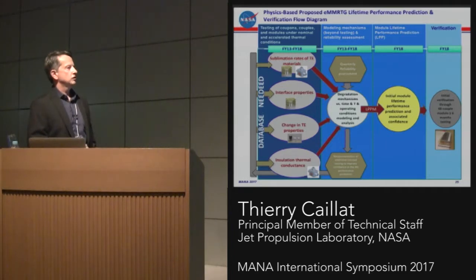So what we use is a physics-based model where we track the different degradation and quantify the degradation mechanisms, which are the sublimation of the materials, the interface properties of a couple, the change of the thermoelectric properties of the skutterudite materials themselves, and the insulation. So these are the 4 key degradation mechanisms that could affect the performance of the RTG over time. So you test for a couple of years. You do this under nominal and accelerated thermal conditions, which is the beauty of thermoelectrics. You can increase the temperature to accelerate the degradation mechanisms, but you need to confirm this is just an acceleration. You're not introducing new degradation mechanisms. By doing this acceleration and quantifying that acceleration, you can model the degradation mechanisms and extrapolate over the life of a generator.